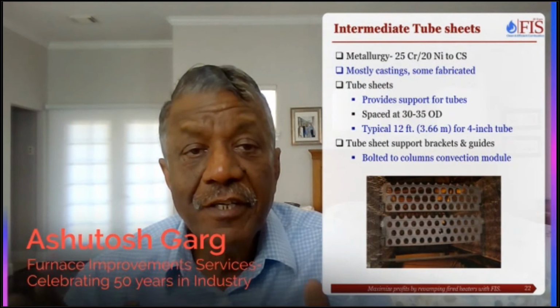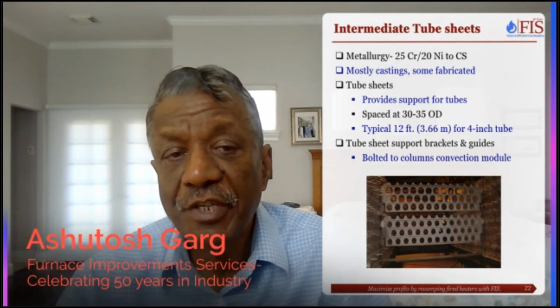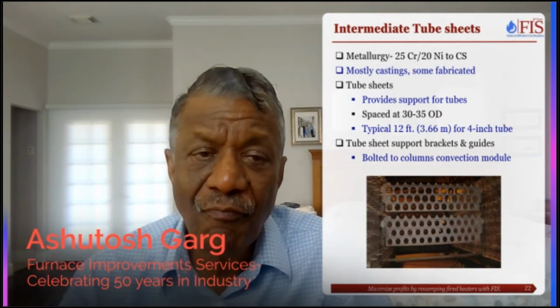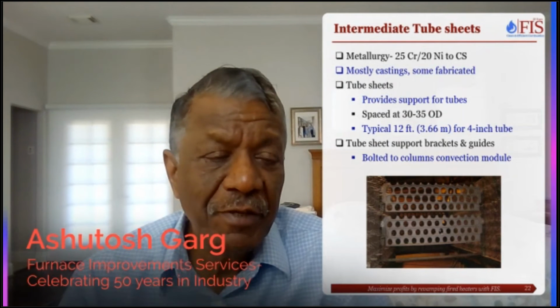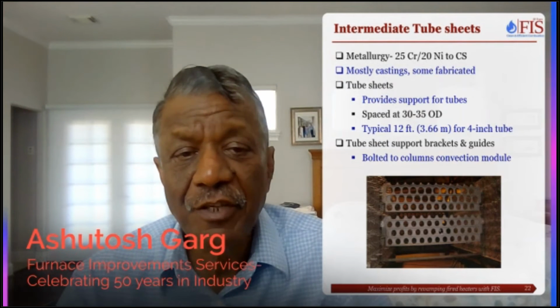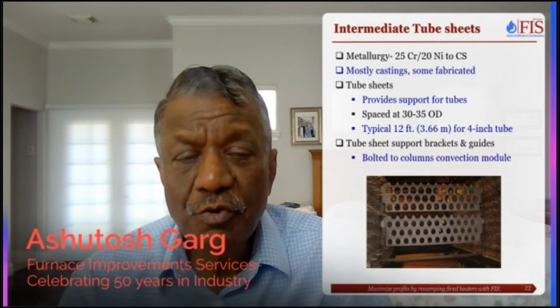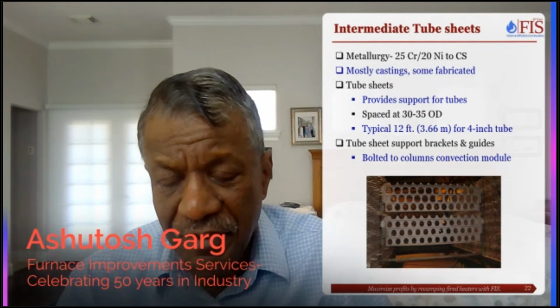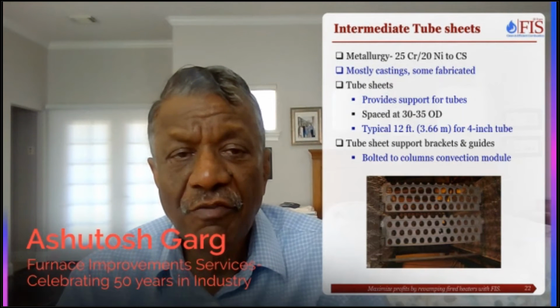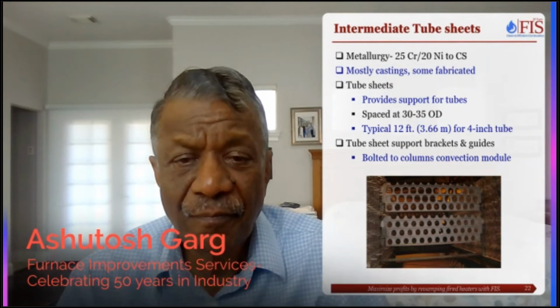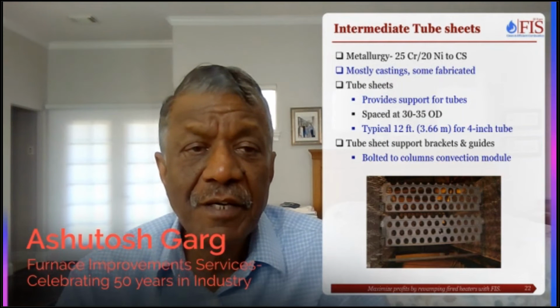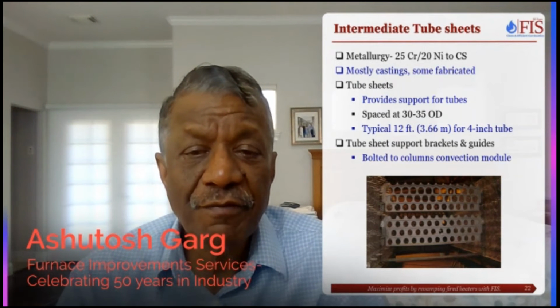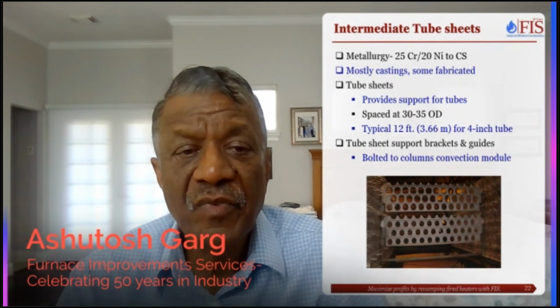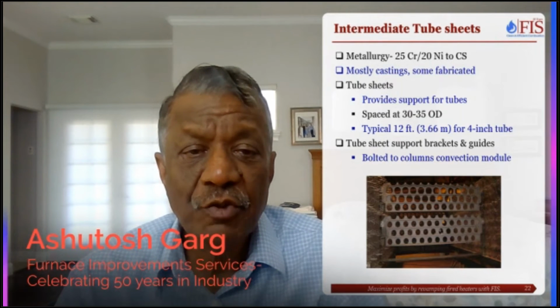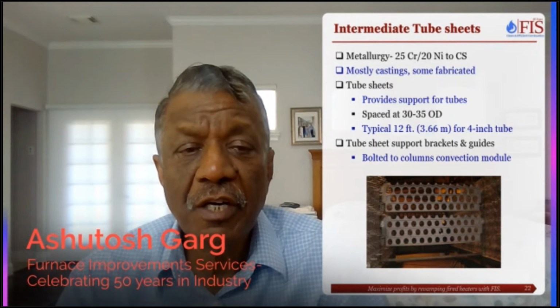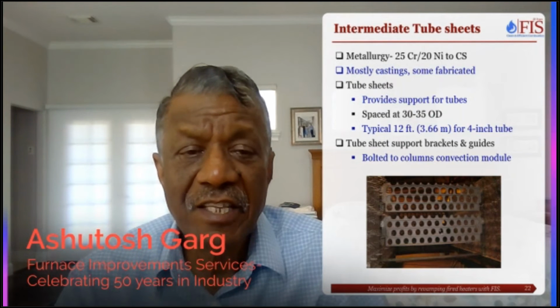Then these horizontal tubes require intermediate tube sheets every 35 OD, about anywhere between 12 feet to 20 feet depending on the tube size. So these castings, intermediate tube sheets are made out of high chrome nickel alloys. Depending on the temperature, sometimes we even do 50 chrome 50 nickel for fuel oil fired heaters, and they are used for supporting the tubes. These tube sheets are bolted to the columns so that they can take the weight.